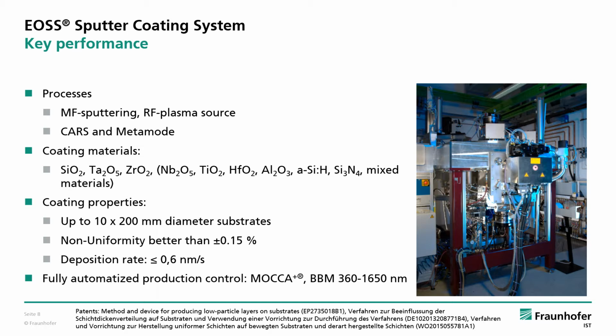The filters were deposited on the EOSS sputter coating system, which was developed in our institute. The process is based on mid-frequency sputtering of thin metallic layers onto a rotating turntable. An RF plasma source oxidizes the thin metallic layers. It is called the Metamode process. We use it for silicon cylindrical targets. In the case of high refractive index materials, tantalum pentoxide and zirconium oxide, we use the CARS process, compound-assisted reactive sputtering. In this case, the targets contain some amount of oxygen also. It is important that we do not use any additional oxygen in the sputtering compartment. This makes the process very stable.